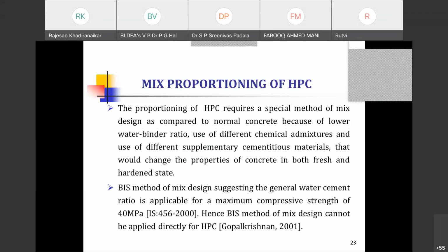Many times what happens is we go for choosing the materials the way we do it for conventional concrete, then that will not work. All the constituent materials that you are picking must be very judiciously picked up, and you have to take very stringent measures for selection of constituent materials. It may be cement, fine aggregate, coarse aggregate, water, mineral admixtures, or chemical admixtures. In all these cases, you have to be very cautious. You might have a very good mix proportioning technique and mixer available, but if your constituent materials lack the basic requirements, then you will not be able to produce high performance concrete.